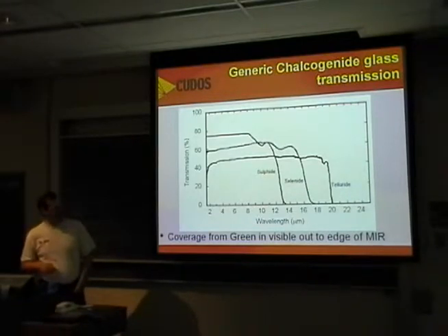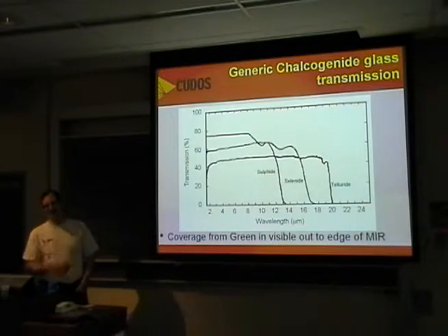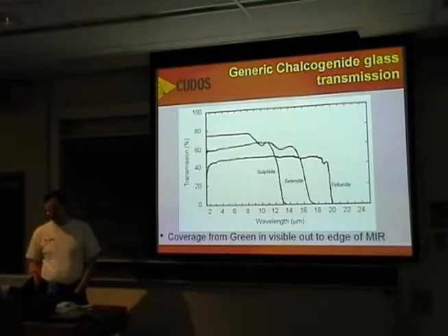And this is basically a result of the mass of the sulfur, selenium, or tellurium atoms. Because this is the multi-phonon edge. The heavier the thing is, the lower the vibration frequency, the further out this way you can go. But what's important about this is that we've got coverage here from more or less the edge of the visible right out into the mid-infrared.